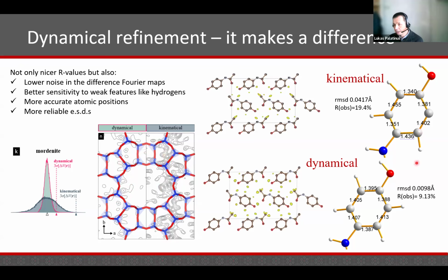And on the right, an example of the refinement of an organic material. So this is a molecule of paracetamol, where the kinematic refinement gives you the right connectivity, but the errors on the bond lengths are relatively large, with a root mean square deviation error of 0.04 angstroms.